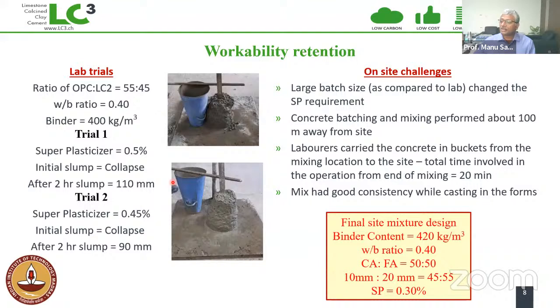You can see the kind of concrete that we produced. We had a fairly good slump, about 110 millimeters after 2 hours. So we designed the concrete with a sufficiently high superplasticizer dosage to achieve the right level of slump. You can see the final site mixture design was a little bit different than what we started off with in the laboratory. That's because of the challenges that we had with the transportation and so on.